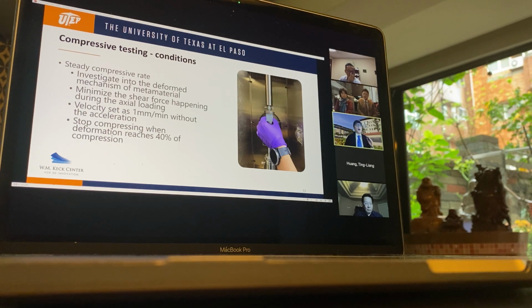So maintaining a steady compressive rate is crucial because the fixture is not really fixed to our sample. Any acceleration of loading will affect the data of the stress diagram. For example, the tilt from the top plate will sense during the compressive testing if we apply acceleration, which will make our data not accurate anymore.